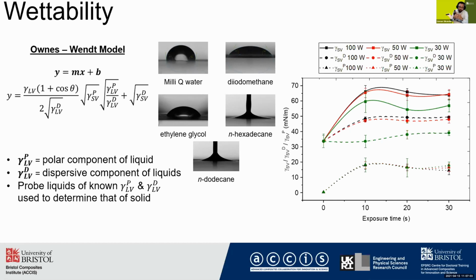And what we found was that at 10 seconds exposure time, both the total surface free energy and the dispersive component and the polar component increase. However, there's no appreciable change at higher exposure times. So this means that the surface becomes more polar as a result of plasma treatment.